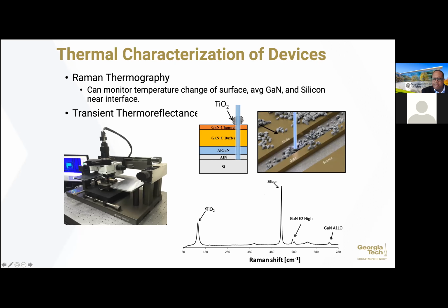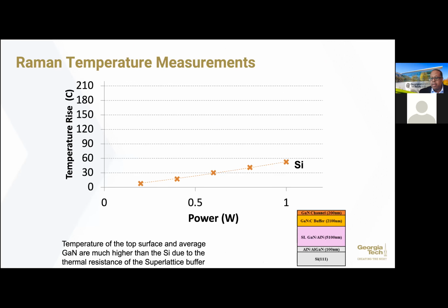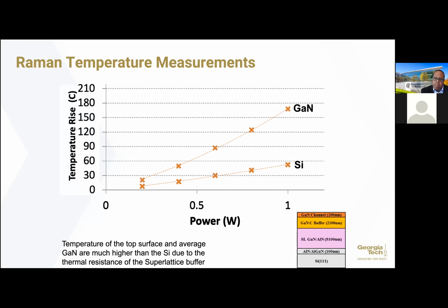What this does is allow me to measure the temperature right at the top of the device, the temperature all the way down at the silicon, and the temperature inside of the GaN. So now I get this vertical measurement of temperature through the device. Here's what's quite interesting. I have a 5 micron thick superlattice structure, about a 2 micron thick GaN layer, and I'm powering this and increasing the power. When I use Raman spectroscopy, I can see the temperature rise in the silicon. When I use the same technique, matching the fingerprint to the GaN, you see a much larger temperature rise in the GaN. This is quite interesting.